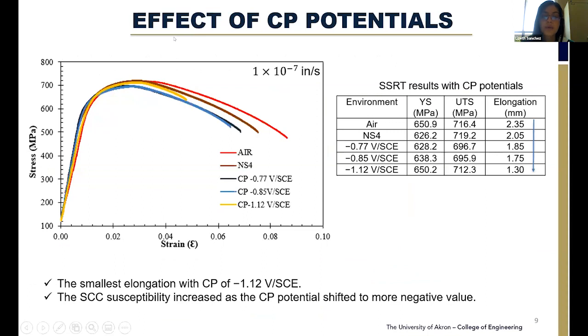First, I ran this experiment only applying cathodic potential. So I had three different potentials, minus 0.77, minus 0.85, and minus 1.12, at this constant strain rate. As we see here, after the sample is broken, the machine gives us a stress-strain curve, so we can see the elastic part and the plastic part of the material, of the metal. And we see how when the potential is more negative, we have less elongation, see the yellow curve. And we have an increase in the susceptibility. Also, you can see that in the elongation chart. So we have an increase in the susceptibility of cracking when the potential shifts to more negative values.